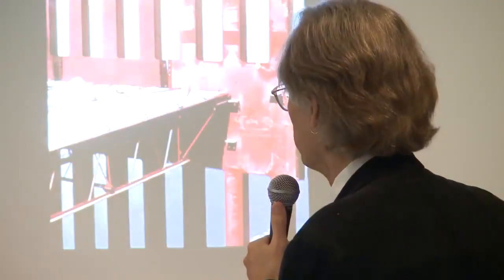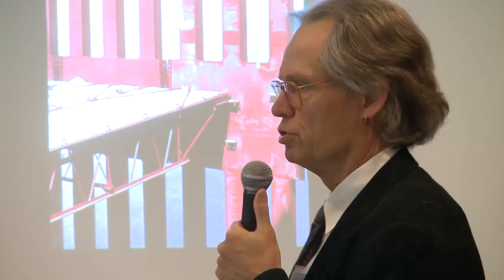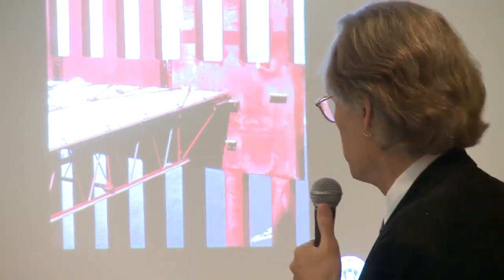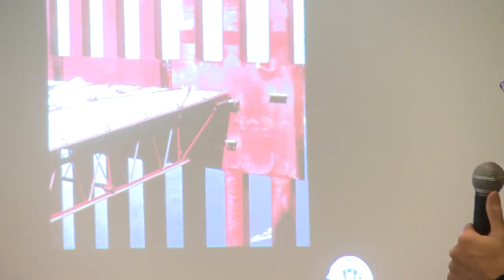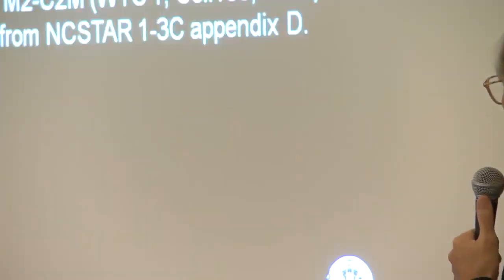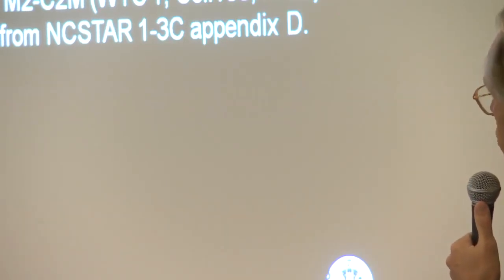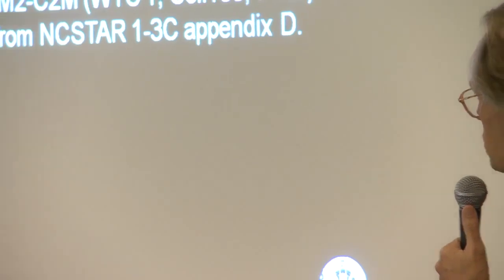And no, it isn't, I can say, because the primer paint applied on the World Trade Center, as you see it here, is what you apply to steel immediately for anti-corrosion purposes. But the primer paint is also red because it does indeed also contain iron oxide, which is red. This is a sample from the NIST report, very specifically isolated. You see the primer paint from the towers. But the same report also contains a chemical description of the composition of the primer paint.